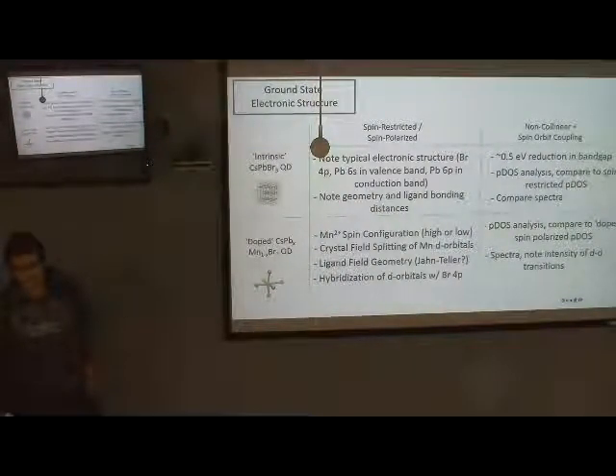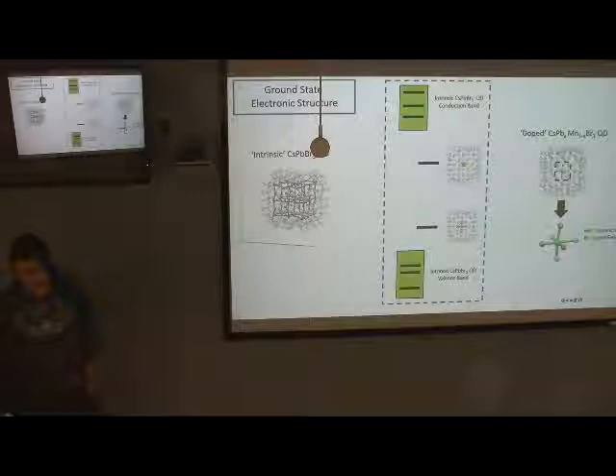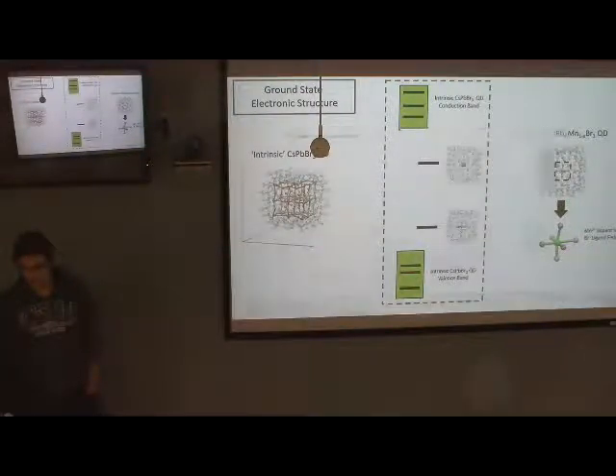absence of. Go to a previous slide. Like here, there are your trap states, right? These are the dopant. Oh, this is doping. These black lines are the doping introduced. But if you don't have doping, then the gap is open. You don't have any trap states. Right. And this is because you really have nice ideal passivation. Mm-hmm. It's like a particle in a box, where you have the finite potential wells on the edge. So it roughly follows that idea. So electron density is inside the cube.